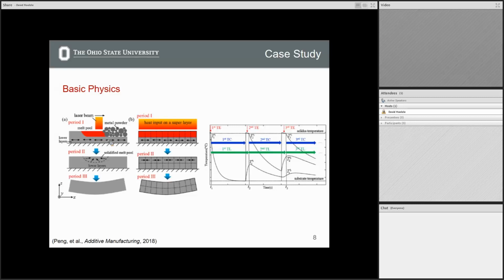So what you're getting is you heat up this build plate. You're creating a melt pool, and directly under the melt pool you are getting very intense temperatures that are just below the melting temperature of that material. That's causing thermal expansion. Then this material on top freezes, and when it freezes, it's essentially at the melting temperature, and then everything is cooling down, and then you get thermal contraction. This is what you get in this area. And so as it's held on the build plate, it has residual stress in it, and then when you cut it off, this is showing the act of cutting it off from the build plate, it kind of rolls up like a potato chip.